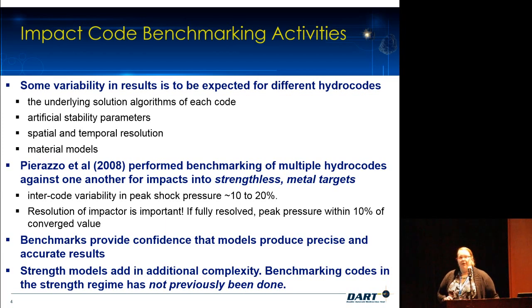However, because of the size of Didymoon and the sort of regime of impacts that we're in for something like DART, we're going to be in what's called the strength regime. And that means that the material strength and material properties are going to be really important to understand the cratering process and the ejecta formation that causes the push. So we wanted to understand then, how do these codes do against each other when you add strength into the problem? And what might that mean for predictions from different codes that have different strength models or different material properties implemented in different ways?